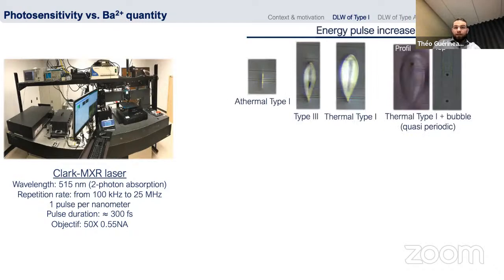Through the increase of the pulse energy, we go through several types of profile of our type 1 modification. First is the athermal type 1 with a very straight line. Then there is some kind of onset of the thermal type 1 with the appearance of some degradation of the glass, so that's why we consider it as the type 3. Then when we increase more the pulse energy, we go to the thermal type 1. And then when we increase more the pulse energy, we have a combination of thermal type 1 plus the observation of self-organized bubbles.